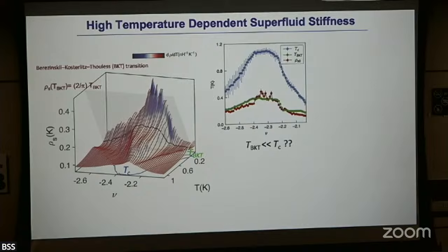Now, practically, when we make the device and measure with a really small bias current, let's say I'm measuring the resistance as a function of temperature with a very small bias, then you will see it is zero and then it goes up something like this. Practically, the very foot of this R versus T curve, close to zero, is where we identify the BKT transition temperature.